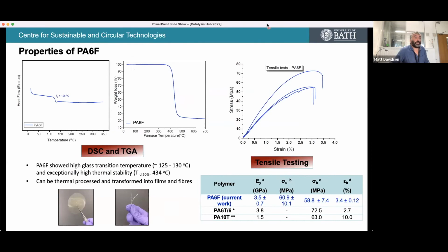And again, I don't want to really dwell on this, but the properties of the polymers that Cameron's been making are really, really interesting. They're competitive with the terephthalic acid equivalents, and I guess the tensile tests here really bear that out. So if you look at the data here, it really is comparable to the commercial polymers that are available using terephthalic acid rather than FDCA as a monomer. They can be thermally processed and transformed into films. They have really high thermal stability and really good glass transition temperatures.